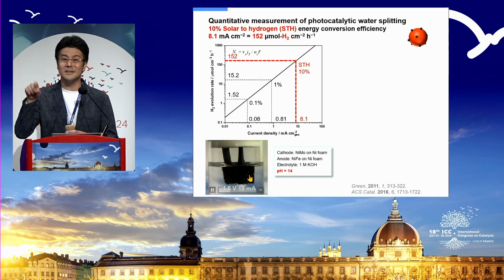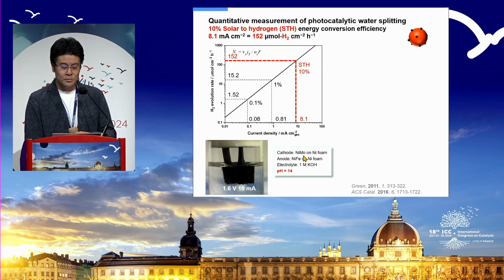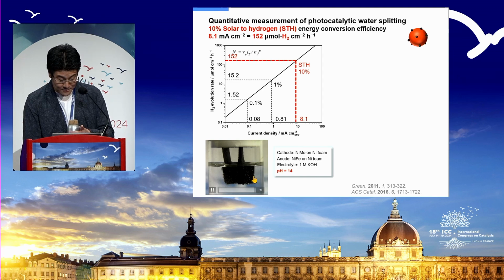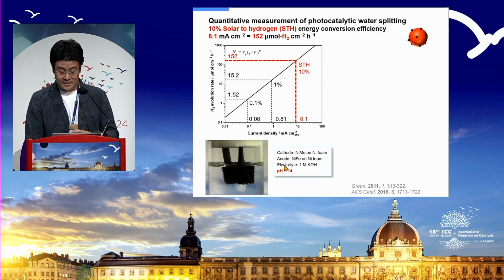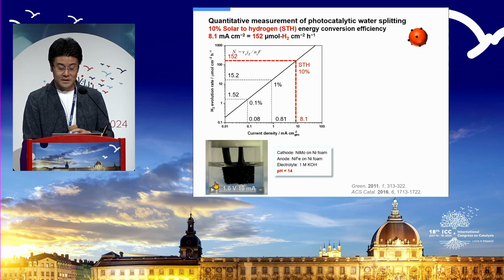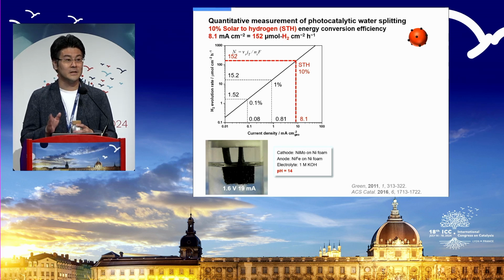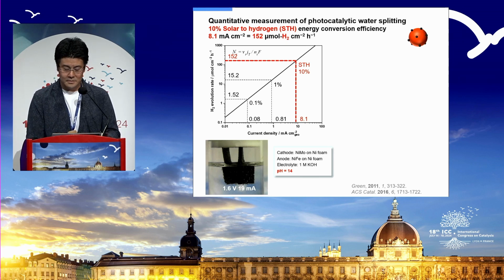This is 1 square centimeter, and I'm trying to use non-noble metals, nickel and nickel-iron-based material. Actually, you're seeing the bubbles. I don't know if you see it. This is achieving 1.6 volt and 19 milliamp, which is already close enough to 10% solar-to-hydrogen efficiency. But you can immediately notice that this electrode is completely black. You can't absorb light if you put this on top of the photocatalyst semiconductor materials.